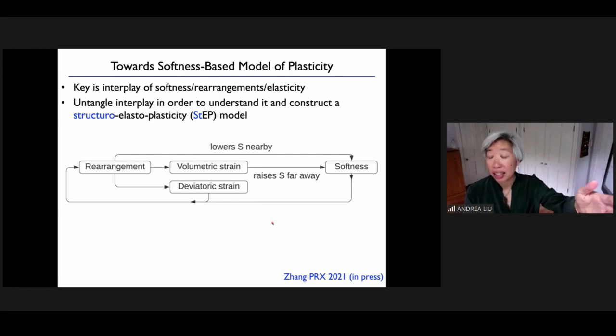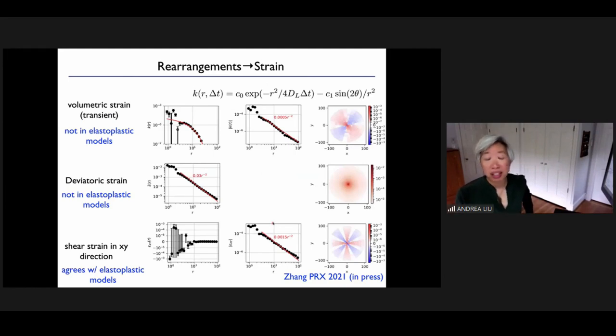And what I want to show you now is how we step through, how we analyze particle simulations in order to derive this model. So the first piece is to understand this, and this is what has been done before with elastoplasticity models: how do rearrangements give rise to strain elsewhere? There are several pieces. One is the volumetric strain, which has a transient piece that is isotropic and a non-transient piece that is dipolar. If I look at the dipolar piece, for example, and look at how it decays with distance, it decays as the expected power law. This is in 2 dimensions. It also has an angular form, which is dipolar.